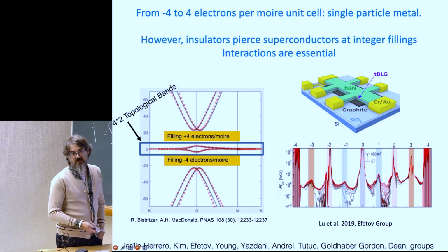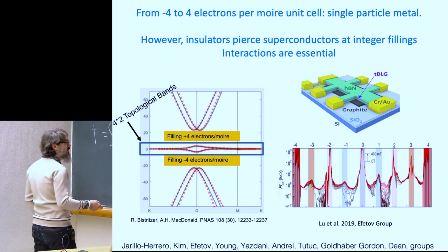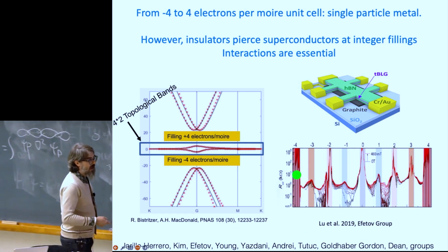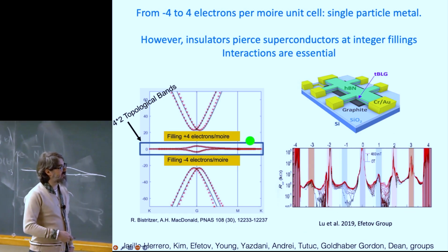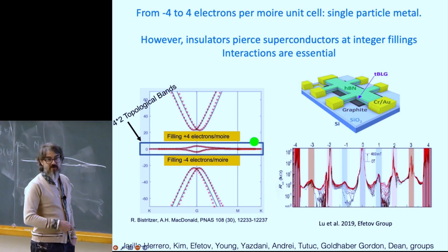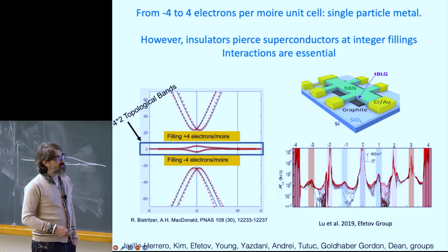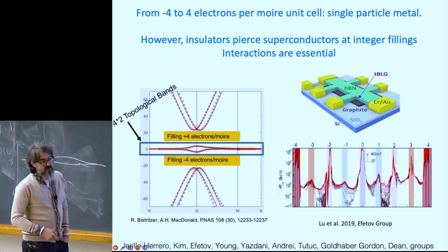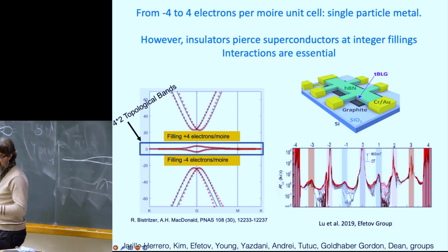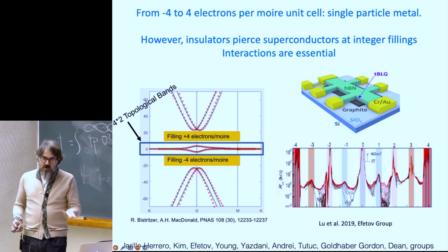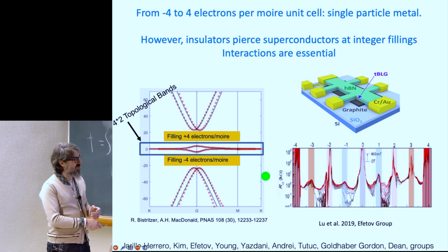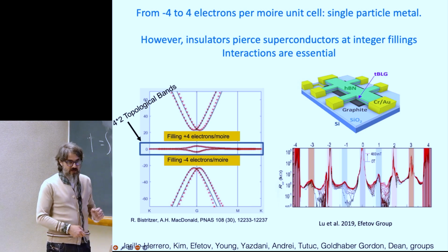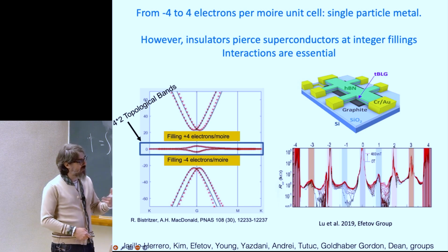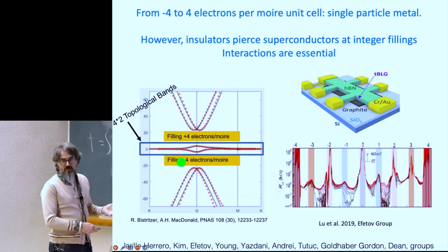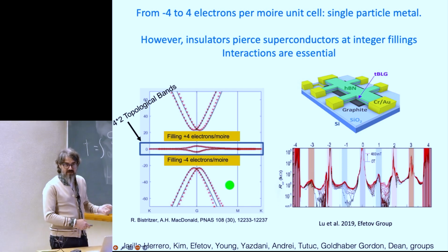It's a superconductor. Okay, so you can see that clearly now this phase diagram doesn't match the single particle phase diagram, which would just be a metal everywhere. And this is due to many body effects. So we knew that many body effects would be important. Why? Because we've quenched the kinetic energy of these electrons. They have no kinetic energy. All they have is interactions, and actually interactions are larger than the bandwidth by a factor of 3 or 4 in this case.